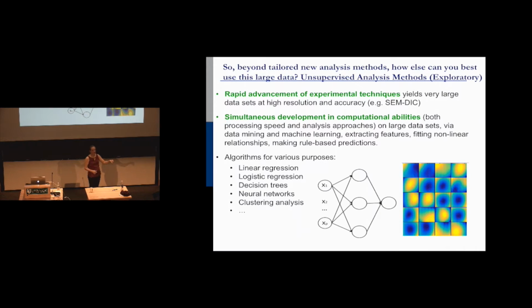At each data point, we have an estimate of damage. That's the strain maps that you saw. You can see how much something has detwinned, right? At this point, x, y, we have this amount of residual damage and this amount of detwinning. So you have the damage map. That's why we broke out the mechanism, so we could get an estimate of damage.